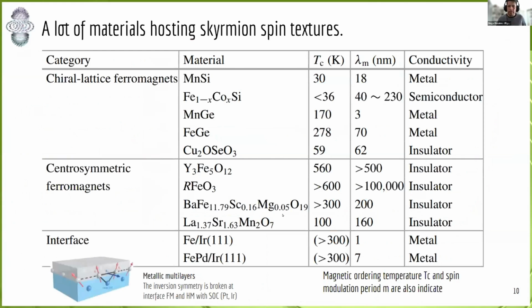And there are a lot of materials hosting skyrmions with different categories or different properties, like metals, semiconductors, or insulators, with different critical temperatures and different sizes of the skyrmion, from a few nanometers to 100 nanometers, for example. The category is related with the main ingredient to induce this skyrmion. For example, in chiral magnets like MnSi, the main ingredient is the Dzyaloshinskii-Moriya interaction, which is related with the spin-orbit coupling. And in centrosymmetric materials, the main ingredient is perhaps the anisotropic interaction or dipolar interactions. And it is possible to induce the skyrmion at the interface between metallic multilayers, where at the interface, spin-orbit coupling induces a strong Dzyaloshinskii-Moriya interaction.